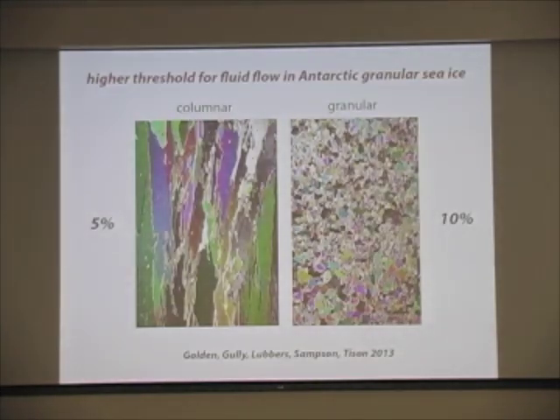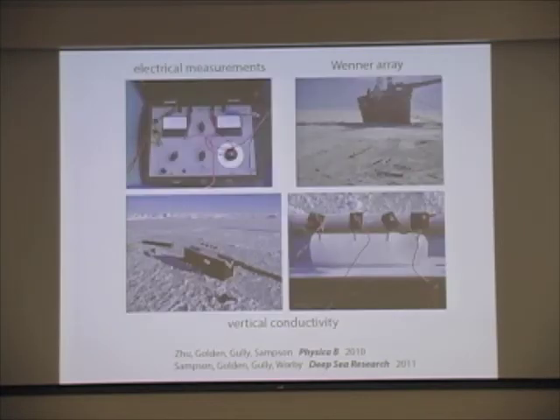One of the cool things we found is that we have a much higher percolation threshold in the fine-grained granular ice that dominates in the Antarctic. And we've actually really nailed that down on our last trip. This is some of our setup for some of our electrical measurements. That's the aurora right there. And anyway, we were the first to actually extract these ice cores and put the electrodes like this.